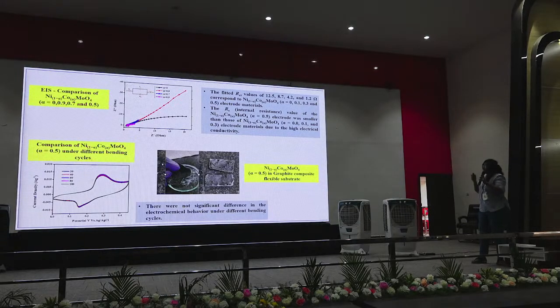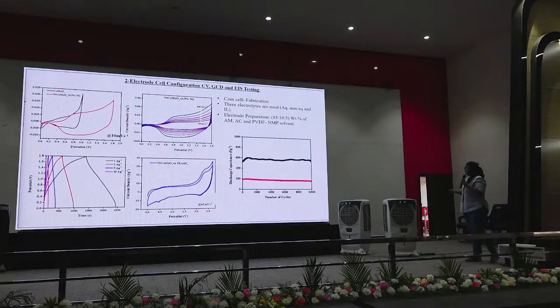Again, I have tried a flexible version with a graphite composite flexible substrate, and I have also done bending cycles. Almost 100 cycles have been done and the cyclic voltammetric technique was performed, and there was no significant difference in the CV. Almost the same capacitance was obtained. That's all about the 3 electrode setup.